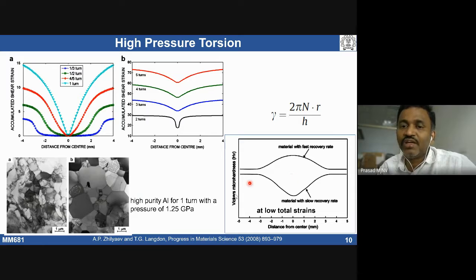So this is the effect of stacking fault energy. How the microstructure is going to develop depends on the stacking fault energy of the material. If we take a high stacking fault energy material, where recovery can take place very fast, that can lead to initially lower hardness at the edge than at the center, as compared to the original hardness of the material. With more and more strain, we can get almost the same hardness in the material, provided we are giving more accumulated shear strain.